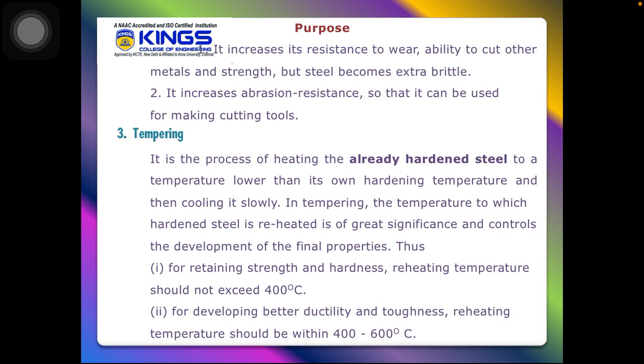Thus, for retaining strength and hardness, the reheating temperature should not exceed 400 degrees centigrade. And for developing better ductility and toughness, the reheating temperature should be within 400 to 600 degrees centigrade.